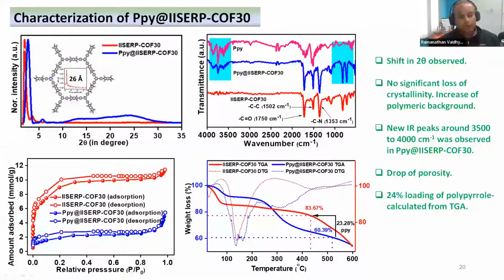Before that, we also find that upon loading the polypyrrole, the COF's lattice itself contracts a little bit, which is counterintuitive in some sense, because you would expect it to swell. But the contraction potentially could be due to the fact that the interaction between the polypyrrole and the walls of the COF is pretty favorable, and they interact strongly and shrink a bit. And also we see that even after loading the polypyrrole, there is a significant amount of porosity left in the material, which means the spongy behavior is potentially intact. And we also see that the material is quite stable. And from the TGA, we find that about 24% of polypyrrole could be loaded into this material.